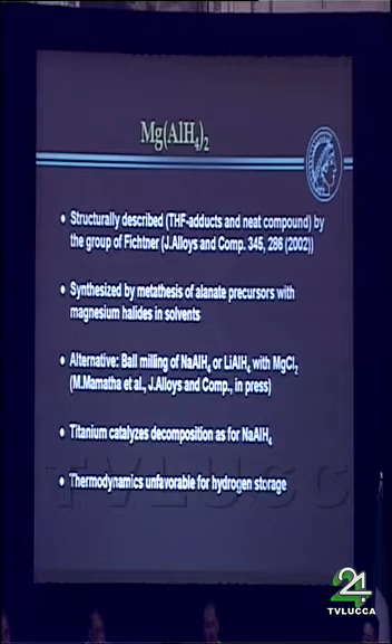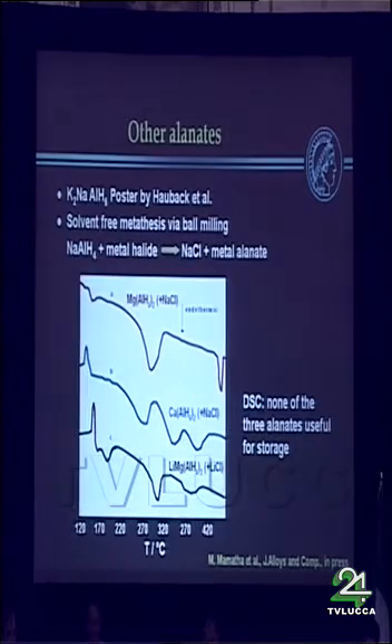I think the important message which Maximilian described in this paper and which we also found is that the titanium catalyzes the decomposition as in the case of sodium alanate. So the titanium action, the catalyst action, is at least transferable to the magnesium alanate system. I would say probably generalizable to all the alanate systems. Unfortunately, the thermodynamics for this system are unfavorable for hydrogen storage. It's not stable enough. It's way too unstable.